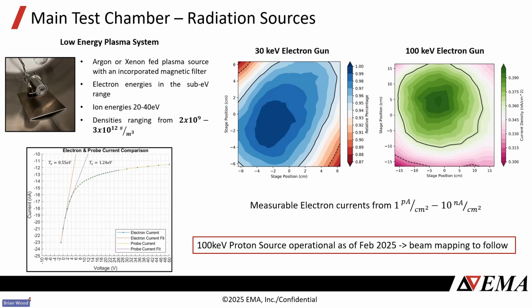And so there's a couple of the beam maps for the 30 and the 100 keV gun, just for reference. This is something we usually always do prior to a project to make sure that the beam map is where we need it to be and that it's uniform. The electron guns themselves can go up to, we say, about 10 nanoamps per square centimeter for the flux, but our measurement with the Faraday cup can be as low as 1 picoamp per square centimeter. And so our noise floor is low enough that we're able to accurately determine the flux when we're irradiating with those lower fluxes, which are usually more indicative of the in situ values that you see.